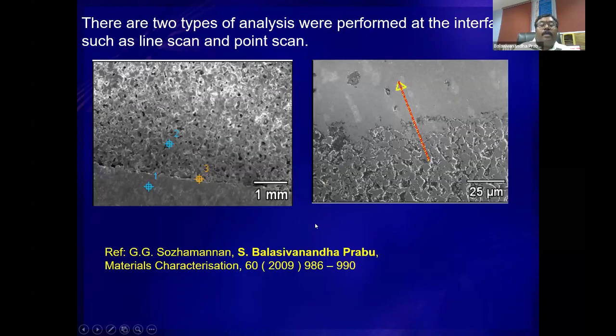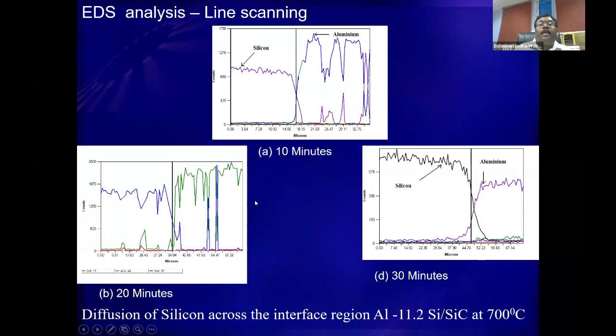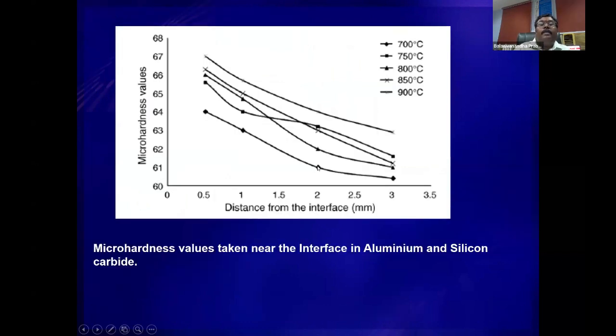So these are some macroscopic images of how it establishes the bonding. And we have also done some EDS analysis to understand how the free silicon modifies the composition of the material. That also we have studied. Finally, we can also study the interface formation with micro hardness examinations. From the interface to away from the interface, we can establish a correlation where Al4C3 formation creates more hardness at the interface. Away from that, it is decreasing, which means it is the hardness of the original material.